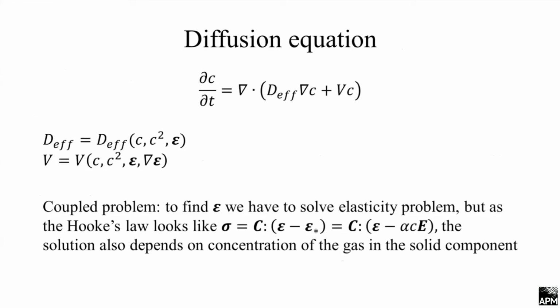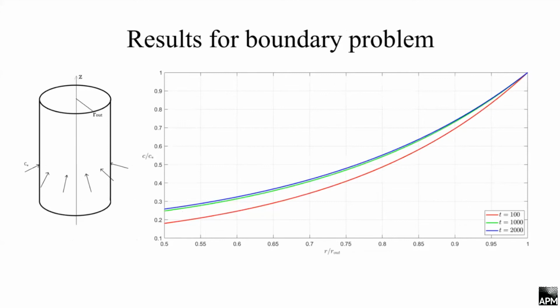To solve any problem, we have to solve a coupled problem, because we have to solve an elasticity problem, and now we have to take into account this induced diffusion strain. What we've done is solve the problem for a cylindrical sample with applied stresses. This is what actually happens in all the fatigue tests of this kind of samples, where hydrogen diffuses from the outer boundary.